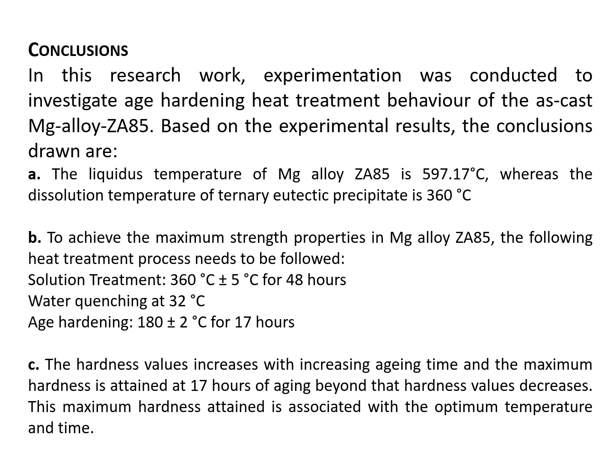To achieve the maximum strength properties in Mg alloy ZA85, the following heat treatment process needs to be followed: solution treatment at 360 degrees centigrade plus or minus 5 degrees centigrade for 48 hours, water quenching at 32 degrees centigrade, and aging at 180 degrees plus or minus 2 degrees centigrade for 17 hours. The hardness value increases with increasing the aging time and maximum hardness is attained at 17 hours of aging. Beyond that, its value decreases. This maximum hardness attained is associated with the optimum temperature and time.